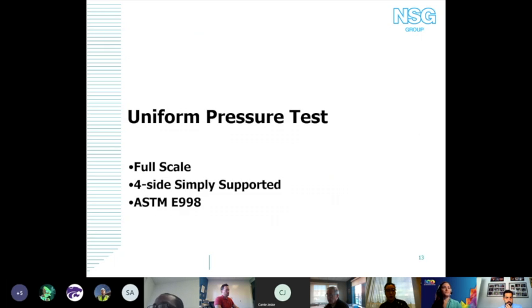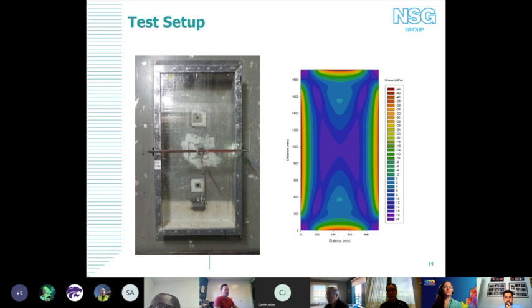So next slide. Now I'm going to move forward to our uniform pressure test. These are just 4-side simply supported tests. Essentially, we had these large scale tests. We put them in this frame and used a vacuum to create a uniform pressure on the surface of the glass. In this case, we were testing everything with the frit in tension because we knew that was essentially where the issue was. And so, next slide.